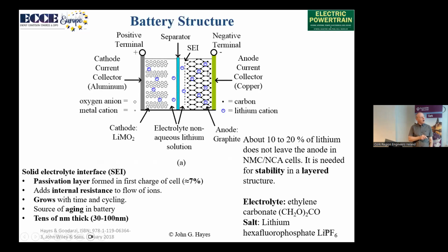And then when we go to charge the cell, we're going to have the lithium move from the cathode to the anode. On the very first charge of the cell, we're going to get a very thin layer that's going to form on the surface of the graphite. That thin layer is actually very useful because it protects this graphite structure. Graphite is just like the lead in your pencil. And it's going to fracture, it's going to break. So now we're putting a very thin layer of lithium on the surface of it. We call that the solid electrolyte interface. It's what we call a passivation layer. It's formed in the first charge.